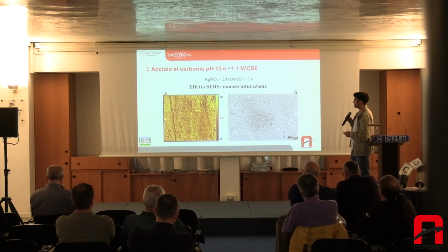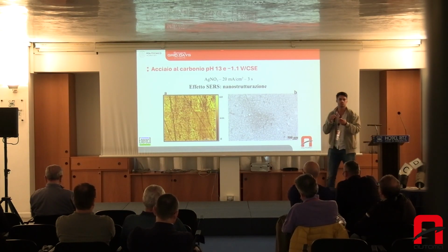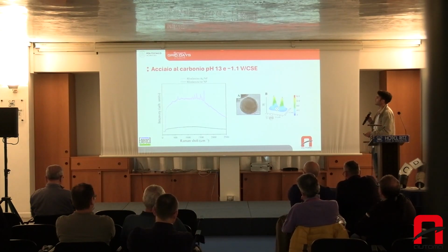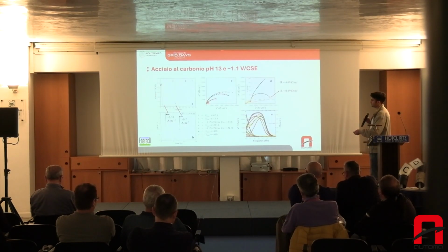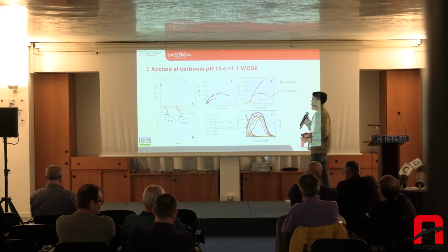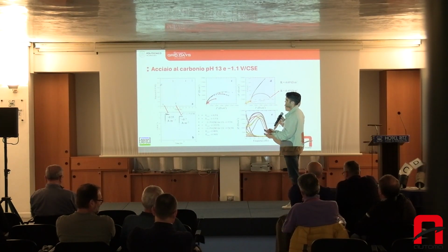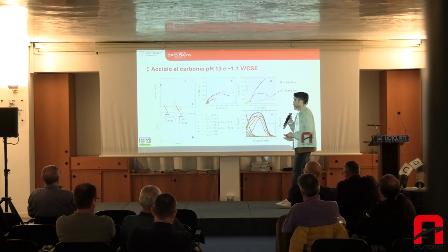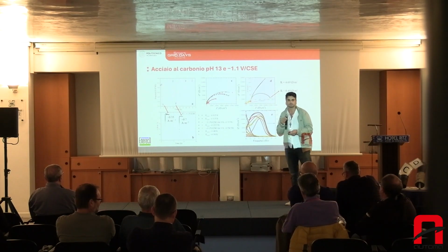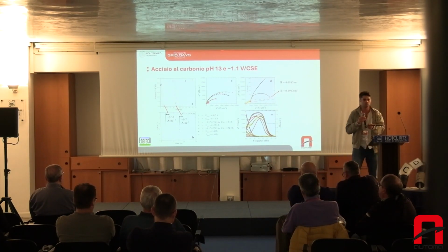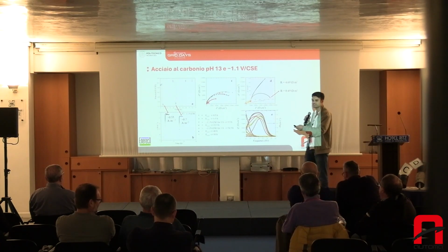This is an improvement we implemented to actually use these technologies as best as possible. Namely, we introduced nanostructures to have more signals from the Raman spectrometer. And these are the peaks that we analyzed that tell us what we have on our tube, on our pipe. As regards the electrochemical values we used, we applied two steps. The currents are quite high. They're very different compared to a tube with a triple layer.